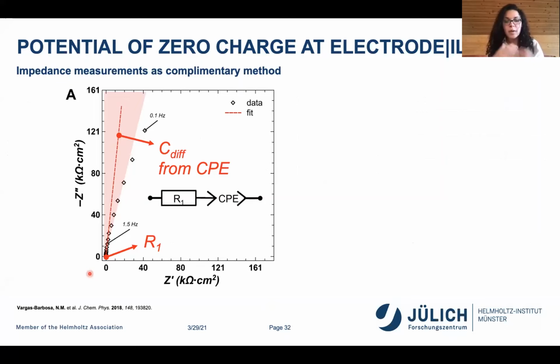And so when you measure the impedance of a system, and these are at fixed potentials, usually at this type of interface, you would get a spectrum that looks something like this. You get a lot of points here in the bottom, and then it starts slowly curving out. And one is not entirely sure how to fit this. Usually in the literature, the way this is done is you fit a resistor and a constant phase element.